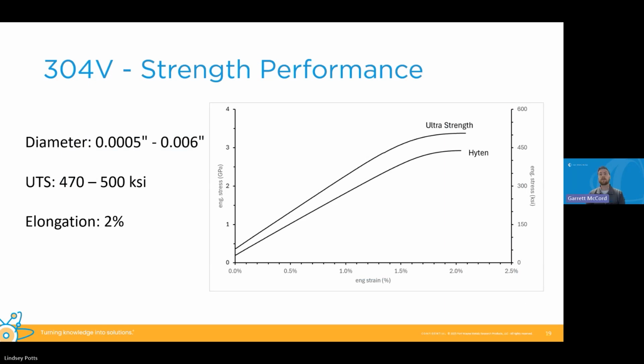To go into the stress strain curve for 304V Ultra Strength, the difference in strength isn't as drastic as the tungsten is. However, with typical Hyten material, which was our previous highest strength material on 304V, we see about a 30 to 50 KSI jump in tensile strength. The sizes that this is available for are about a half a thou up to 6 thou inches, and we've been able to reach about 500 KSI while still maintaining pretty good ductility of 2%, which is very close to Hyten condition as well.